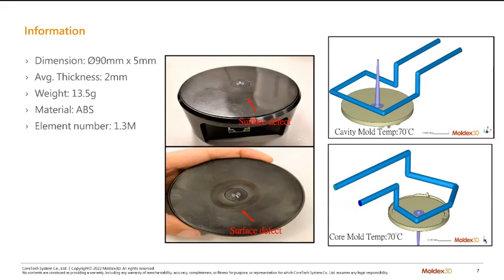Okay, the first one, the stretch mark. In this one, you can see that they have a surface defect. At the very beginning, they didn't know what this kind of defect is. It's just a surface defect. They didn't know if it's a flow mark or stress mark, or maybe it's caused by the material. So here is the basic information: the material is ABS, and the average thickness of this part is 2 millimeters, and you have very simple cooling channels on the top and bottom of the cavities.